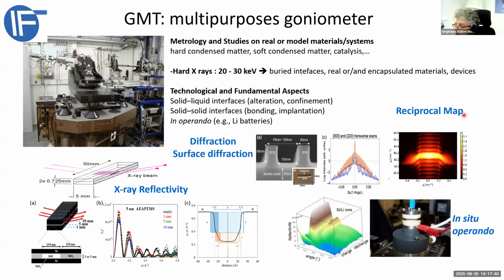So reciprocal space map on thin samples or maybe not so thin samples. You can do some diffraction, so surface diffraction. You can do X-ray reflectivity, and I am going to give you more details on this. An asset is that thanks to X-rays we can monitor by in situ or operando experiments how the structural properties are changing with the external parameters, for instance. And now this instrument is really improved and heavily used for the study of interfaces.